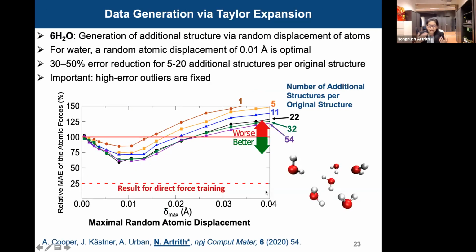We also test what distances we should use and introduce in each structure. In this case, the data generation is for water 6 molecules, and there are so many different data points in the training set. So what we did, we randomized atomic displacements and varied from very small distances until we found the best distance that can be applied to a water system here. You can see that introducing 0.01 angstrom gives the best results, looking at the mean absolute errors of atomic forces, the best performance. At the same time, we vary the number of structures to include in the training set. So more structures also give better results, good force predictions too.